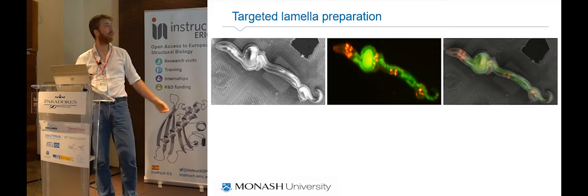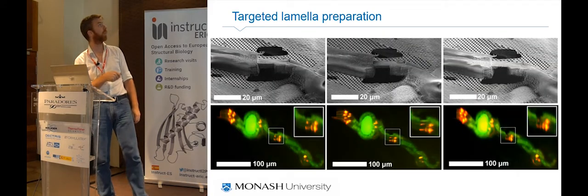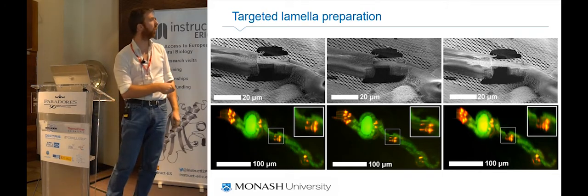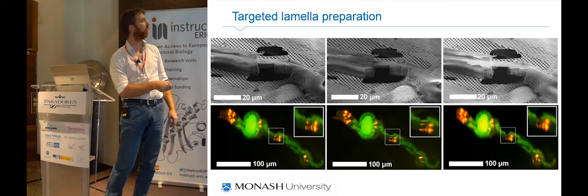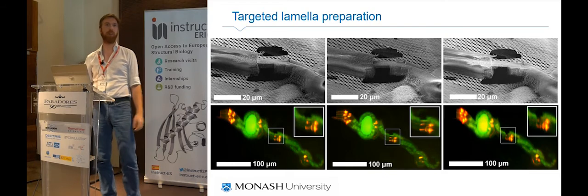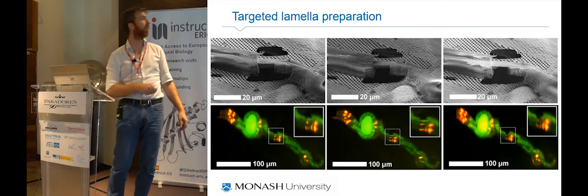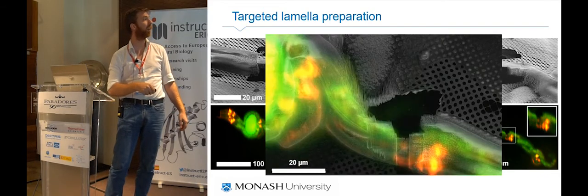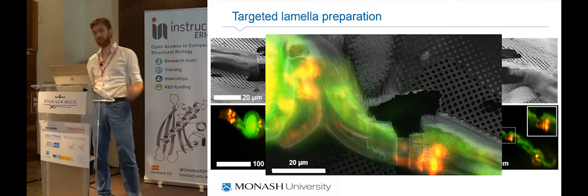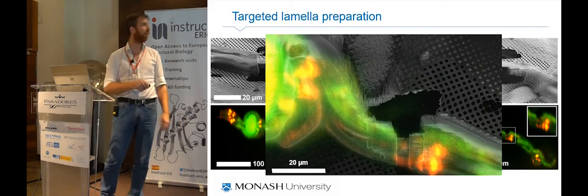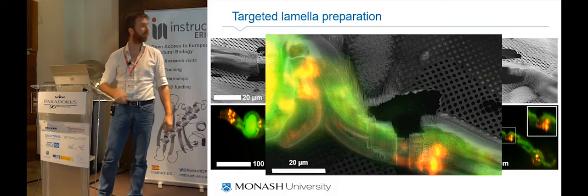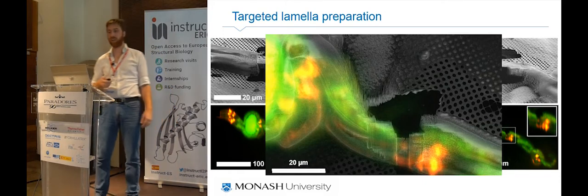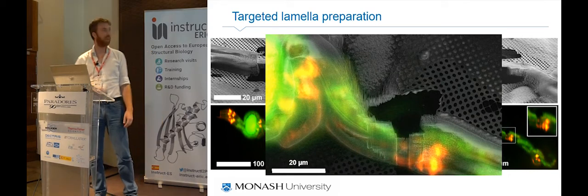What we do is that we decided to go and cut a lamella in this area. So that's how it is. We cut a lamella through the worm, and you can look. At each stage we could check whether our cell was still in the lamella or not. And basically we can go to the end of it, and we have a lamella, and we still have some fluorescence in there. This was a thick lamella. It was meant for X-ray. Didn't ever make it to the synchrotron because it cracked and died on the way. But it actually works.